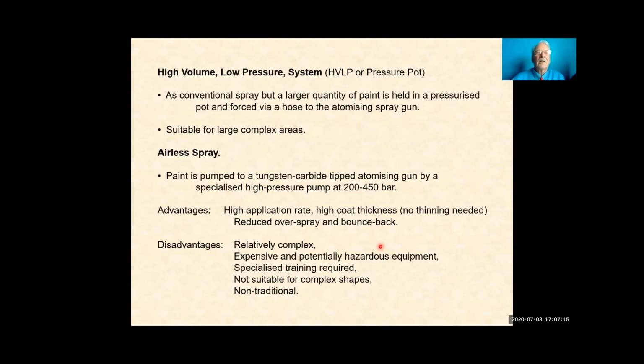You can put a higher pressure into the pressure pot and that will work better. You get more paint coming out. Airless spray, you pressurize the pot itself to a very high pressure, as you can see, 200 to 450 bar. So you get a tremendous delivery rate. It does bounce back at you.